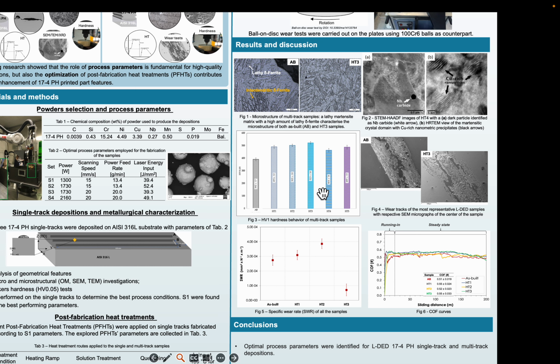Their presence results in the achievement of the maximum hardness of the sample, about 35% above the as-built, as in the case of the HT5, as we can observe. In the case of the HT3, the highest hardness was identified and correlated with the high presence of the martensitic distribution across the microstructure.